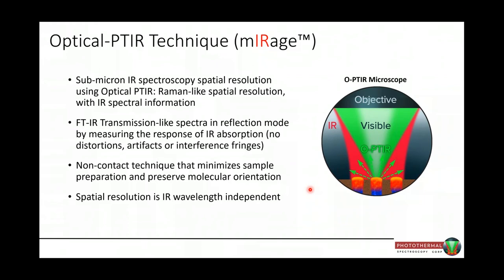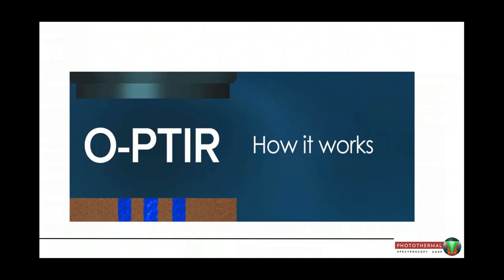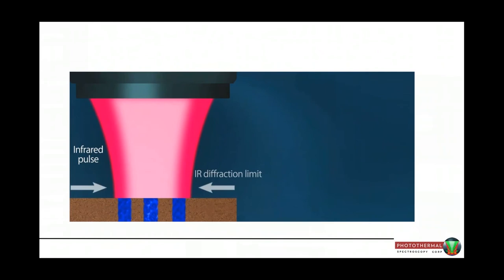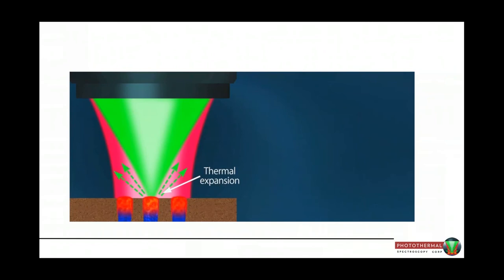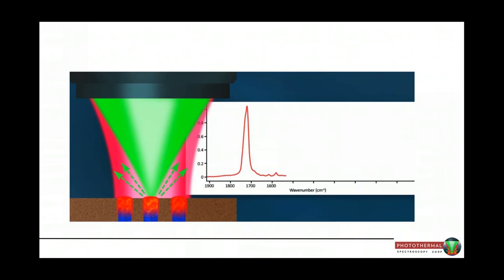So this is a little video that shows how the capability works. The sample has IR absorbing regions and non-absorbing regions, showing in blue and brown. As you put the infrared pulsed laser source on the sample, it illuminates a large area defined by the diffraction limit. We send a second probe laser through the exact same optical path, but it focuses to about a 20 times smaller optical spot. And we look at the reflected green laser light to get the infrared spectrum, which we can record in a matter of a second if we want to.